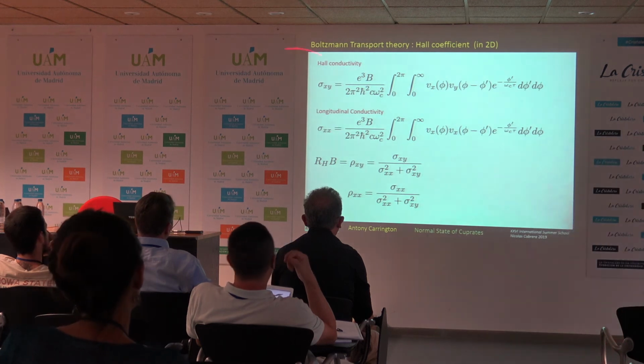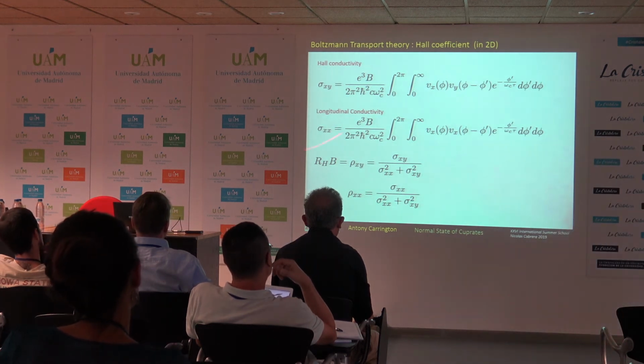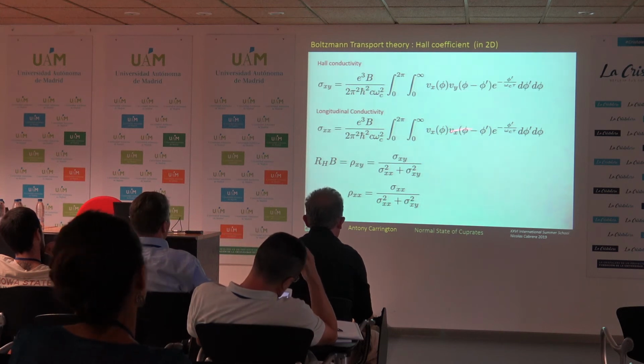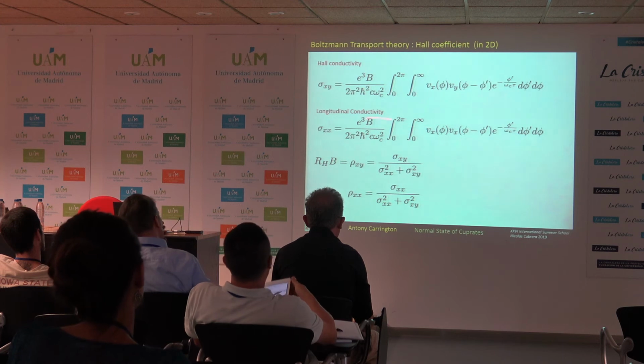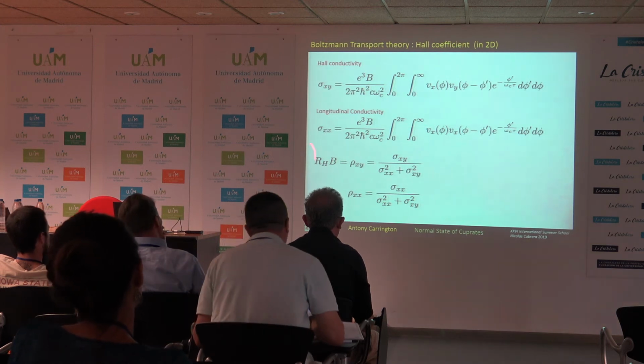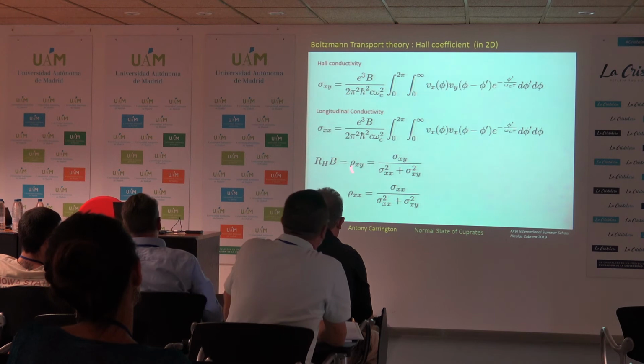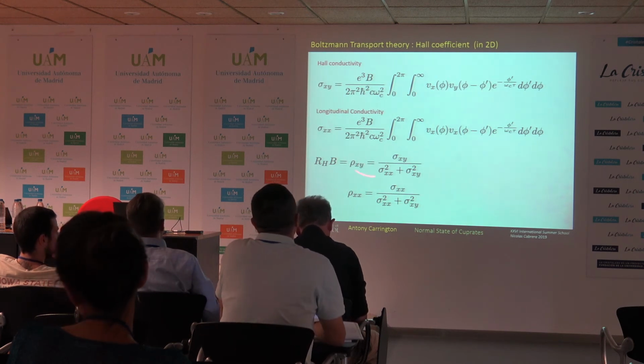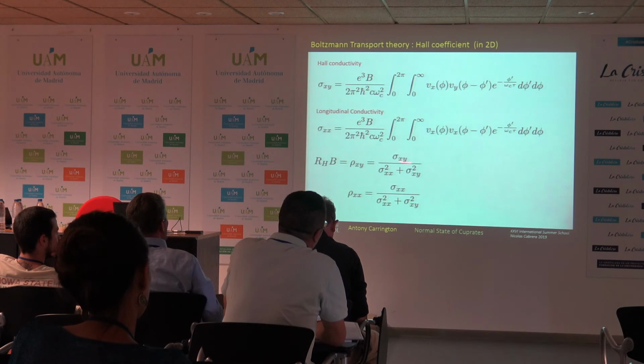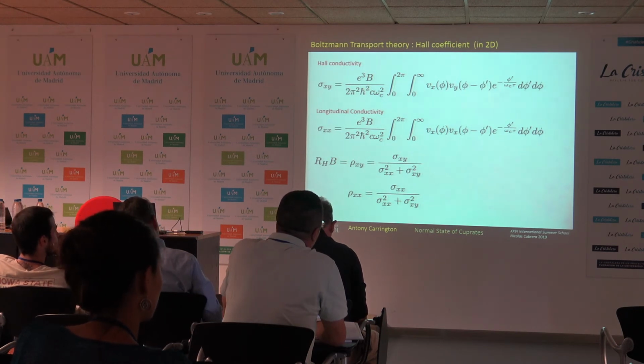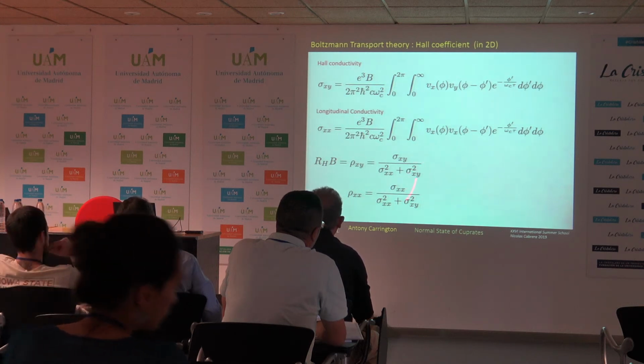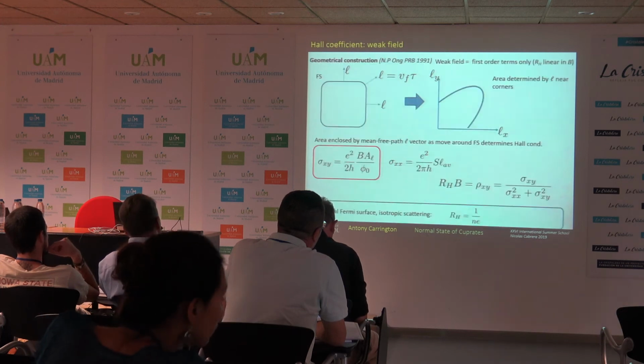Okay, so that's the expression for the Hall conductivity. To get the longitudinal one, you simply replace the y here with an x. This will give you the longitudinal conductivity, the magnetoresistance. And then to calculate in 2 dimensions at least, the Hall coefficient, you just take the ratio of sigma xy over sigma xx squared plus sigma xy squared. And the resistivity is the same but with sigma xx on the top.